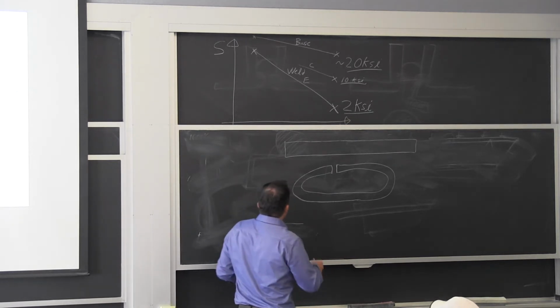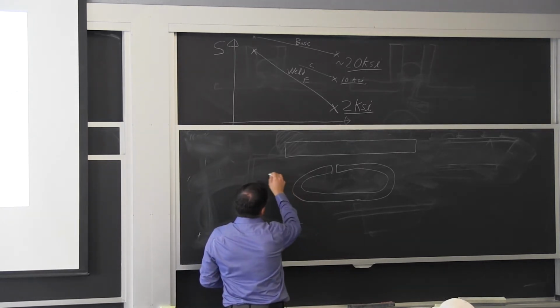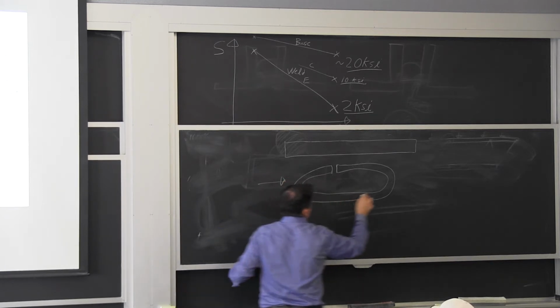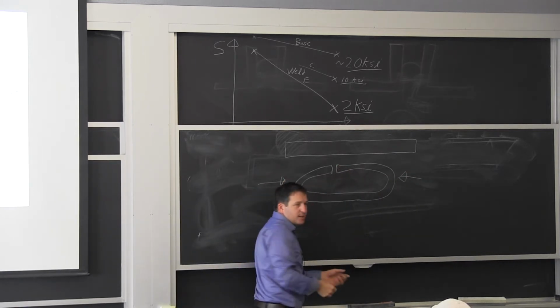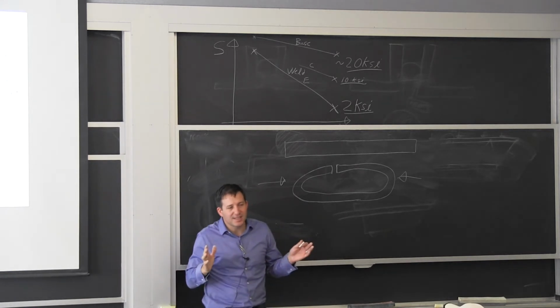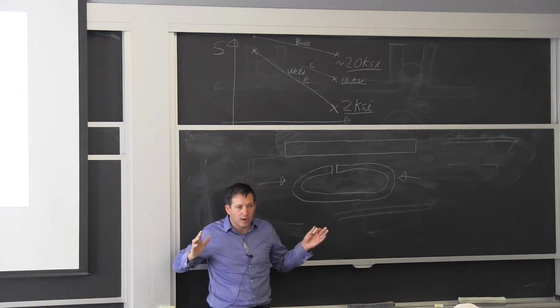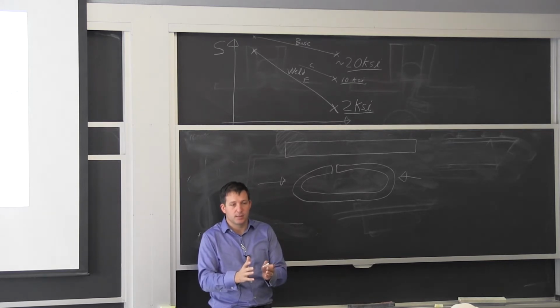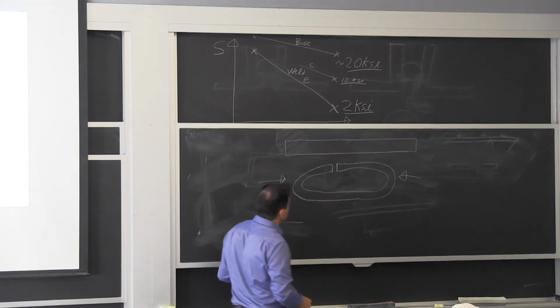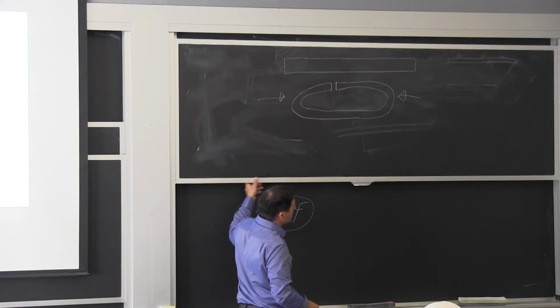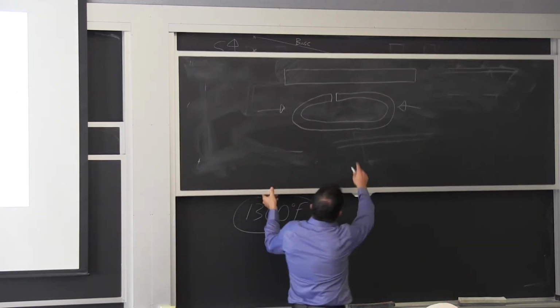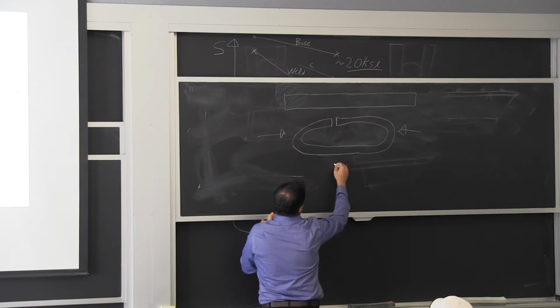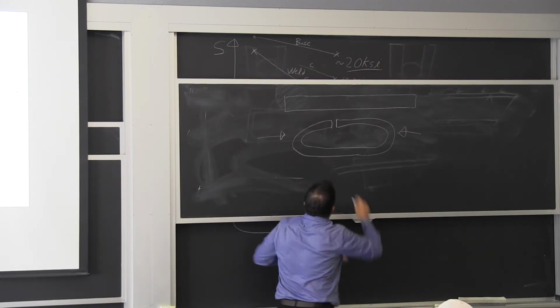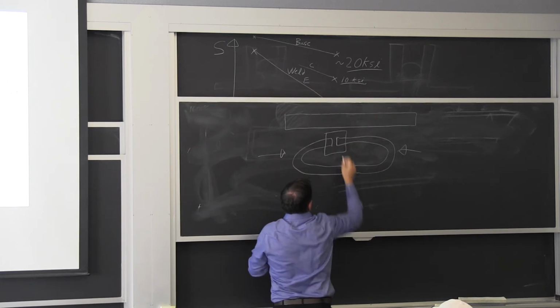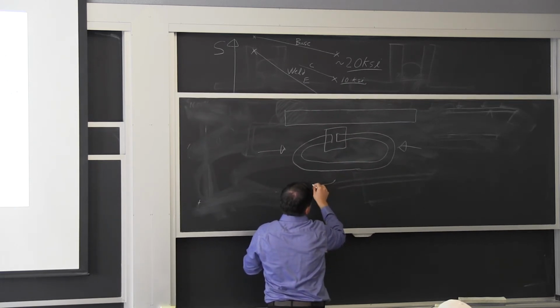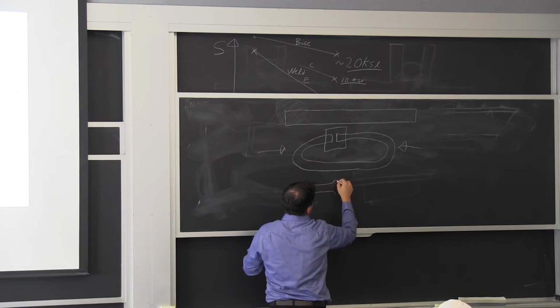Now, what is very important in this flash welding is to apply force, because if I'm melting and I just let it go, it's going to drop. But the idea is, at the same time that you generate the arc, you push the two pieces against each other, and it will create a deformed zone. If you look at that chain carefully, after the fact, you're left with extra metal. So if I look at this zone, I have one side that has extra material, and same for the other.